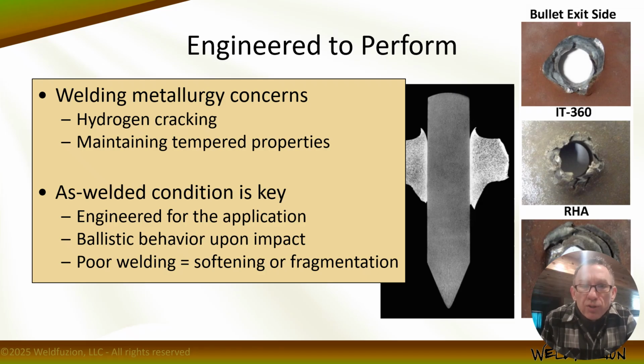So if we cool these materials faster than the critical cooling rate, whatever that might be for the alloy, we could create a more brittle microstructure, especially in that heat affected zone, and that could be prone to cracking and or fragmentation in the event that it is tested, because these things are tested how? In real life conditions when it matters. So hydrogen delayed, cold, or underbead cracking all mean the same thing. They indicate that hard, brittle microstructure, a loss of ductility, and while that is strong and hard, it is brittle and sensitive. And what we're trying to maintain here is a sense of ductility.